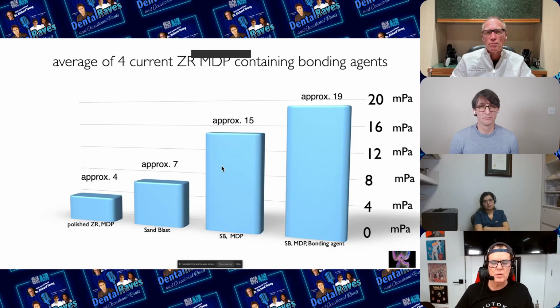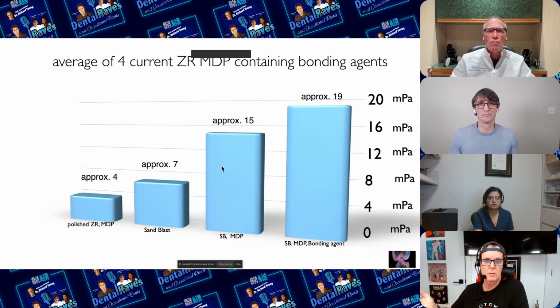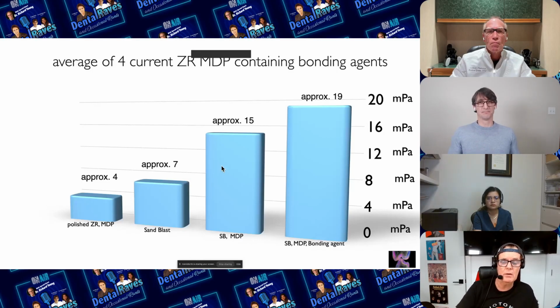Okay, then the third group was classically what people would do. They would sandblast, put an MDP primer on, and we got roughly around 15-ish megapascals, plus or minus. Some of the specimens up around 20 megapascals bond strength, okay? Some of the specimens maybe down around 10.